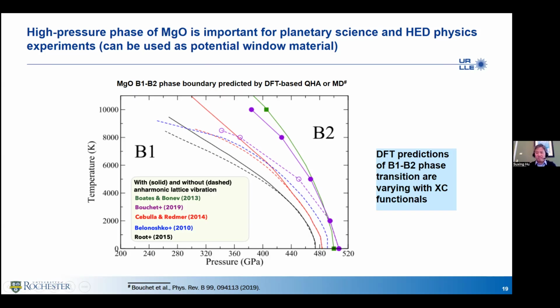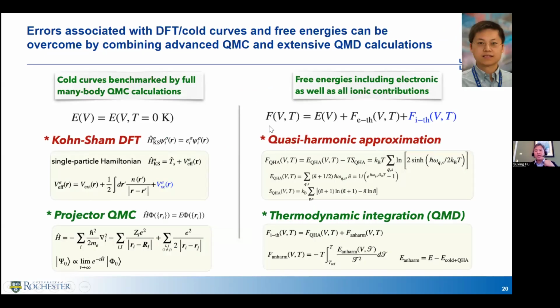Even for the zero temperatures here, all the way to 510 GPa. And the boundary can be even more spread if you go to a finite temperature. So what Sui is trying to do is say, well, how about we combine a QMC method with the DFT or DFT-based QMD calculation, so see if we can pin down this transition boundary.